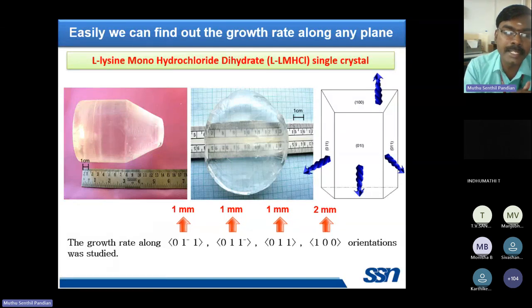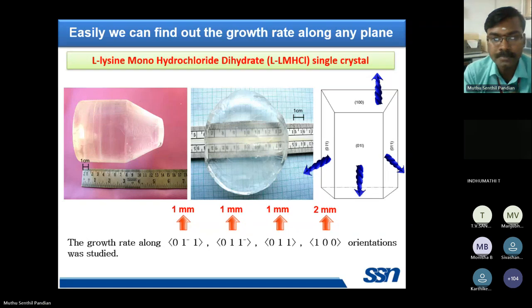So everything should be identical. The seed crystal and then the glass ampoule size, ID and OD, inner diameter and outer diameter, saturation solution level, temperature at the top and bottom portion, everything should be identical. Then you can easily measure the growth rate along any different plane.